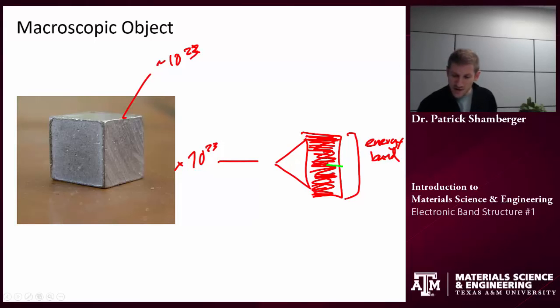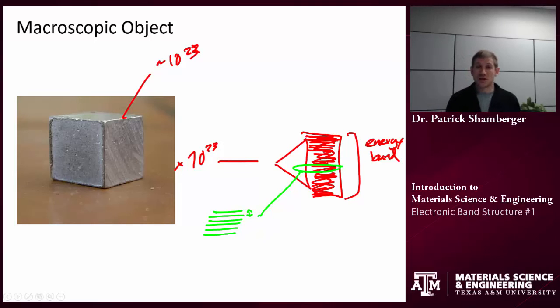And that continuum is what I call an energy band. So if I looked very, very closely in here, I would see a lot of different potential orbitals, potential energy levels that those electrons could occupy. But the separation between them is very, very small, such that if I'm measuring them with any sort of realistic measurement system that I could think of, there's no way for me to separate out this energy level versus this energy level. And so that's why we think of them as this continuum, this band.